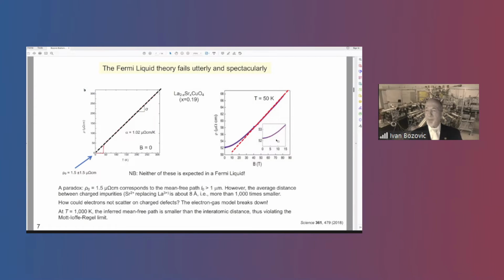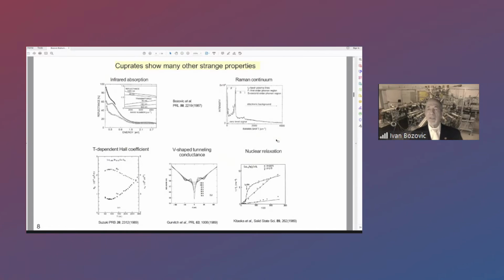The right plot here shows the dependence of resistivity on magnetic field strength, and it also becomes linear in high fields and doesn't saturate up to the highest field we were able to measure, which was 80 or 90 Tesla. And this also is unlike in ordinary metals, where it should be parabolic, and it also indicates the breakdown of the Fermi liquid theory. But that's not all. There are many other properties that are also anomalous.